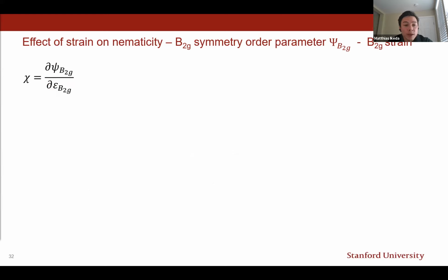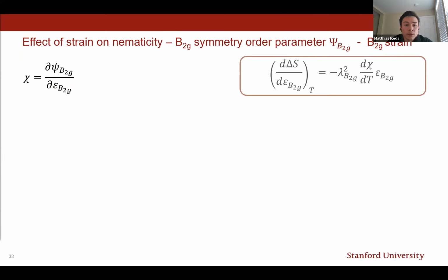Now, the elastocaloric effect measures entropy change as a response to strain and therefore should be ideally suited for this task. I will spare you the mathematics, but it is really straightforward to calculate the elastocaloric coefficient in the B2g strain channel from a Landau free energy expansion around the phase transition. And we find that the elastocaloric effect should be proportional to dχ/dT and also to λ squared, where λ is the nematoelastic coupling constant, and also to the amount of B2g offset strain we applied.